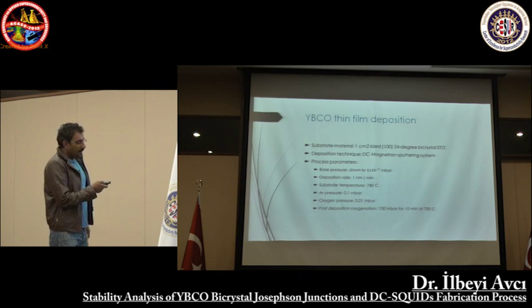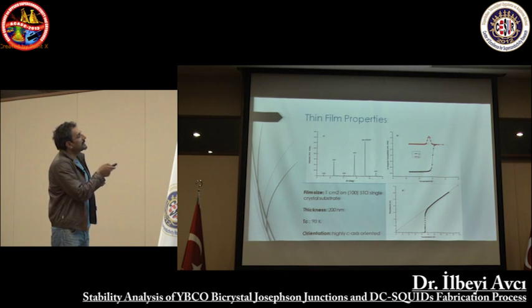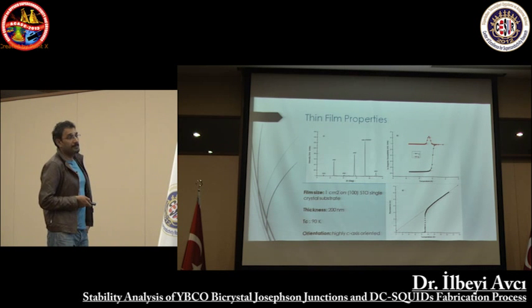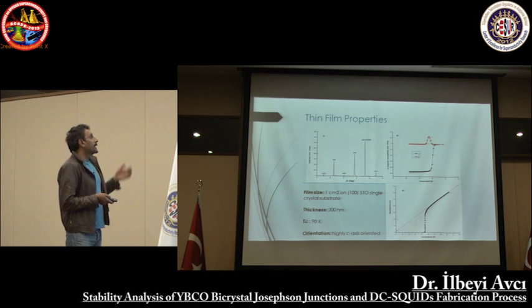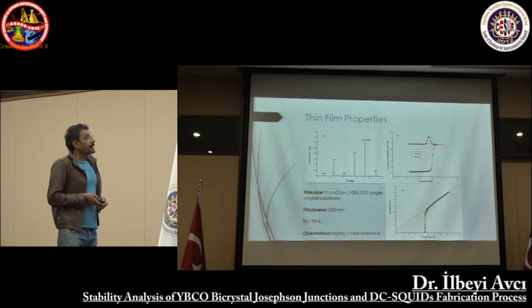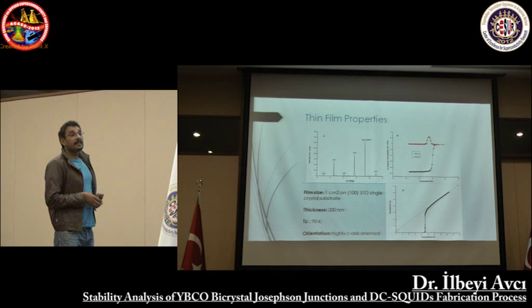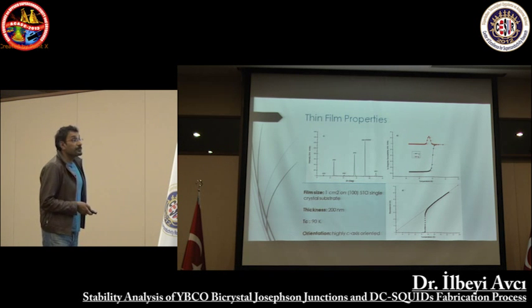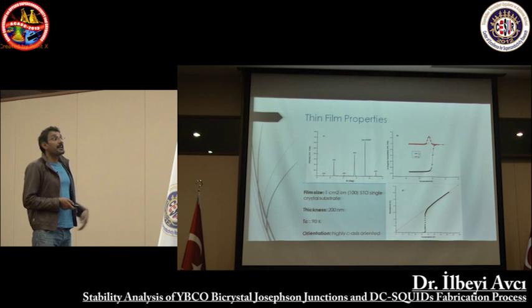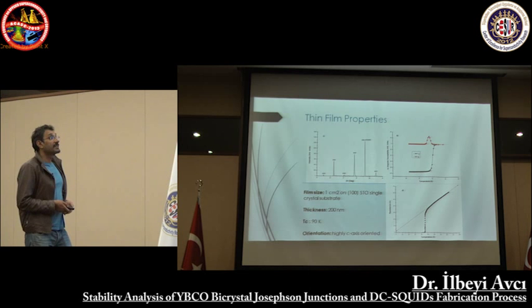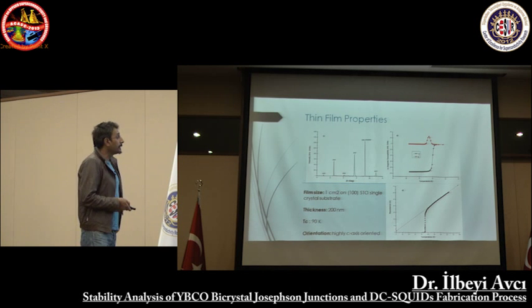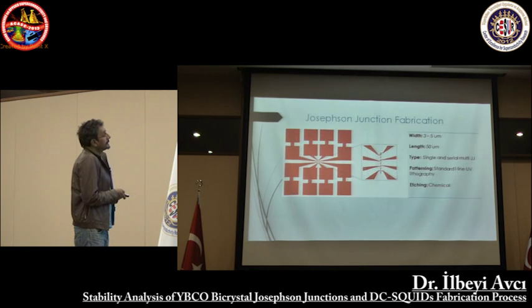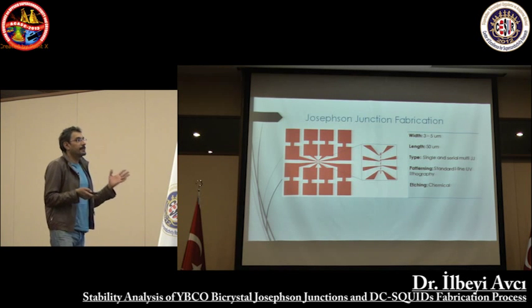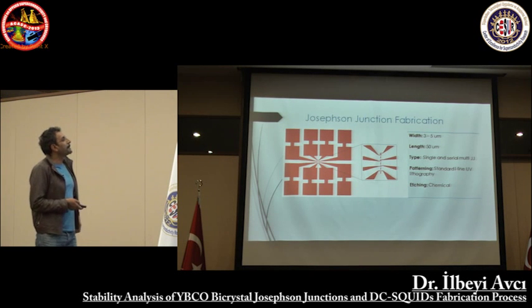With these optimized values, we got this type of thin films. They are highly c-axis oriented with a very nice transition. The Tc is around 90 Kelvin with a very narrow transition width, which we can say is much lower than 0.5 Kelvin. The thickness is about 200 nanometers.